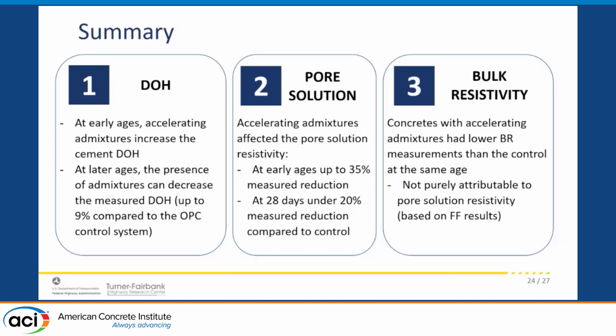The pore solution effect is greater at the early ages. Over time, the effect of these admixtures lessens. The bulk resistivity, we can see the control is always higher compared to the ones where we add admixtures that accelerate the reaction, but it's not only a factor attributable to the pore solution.